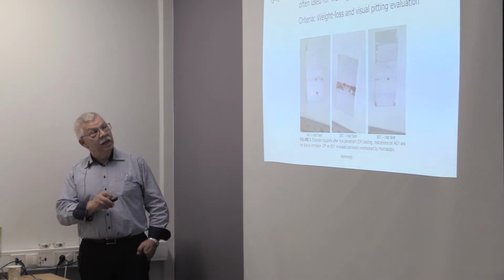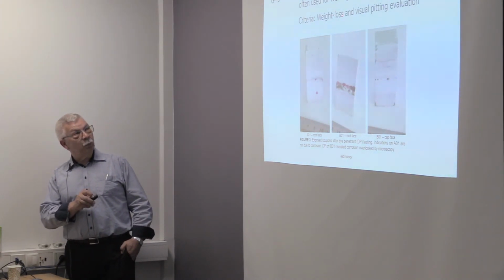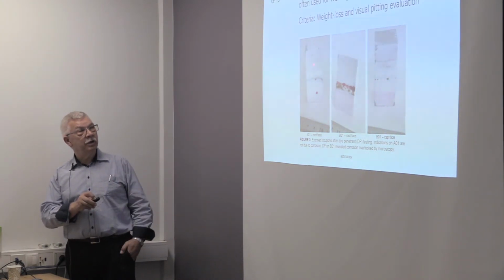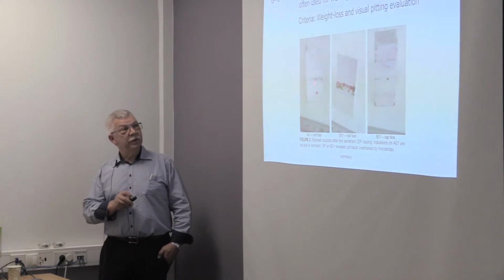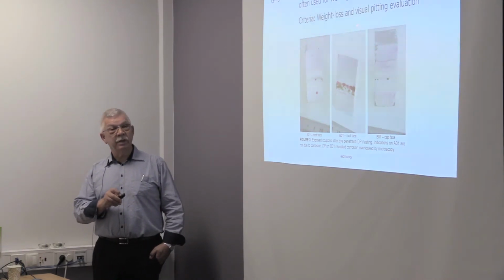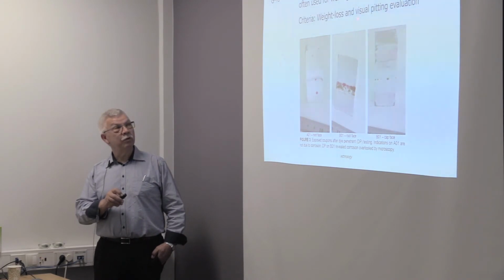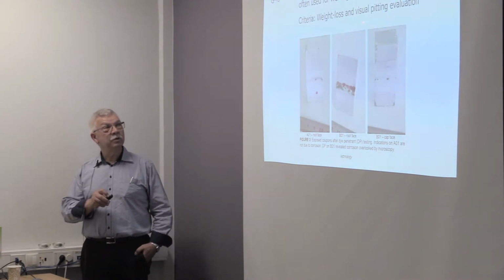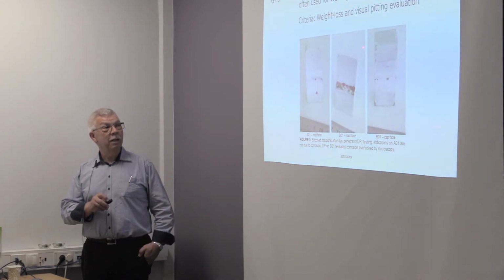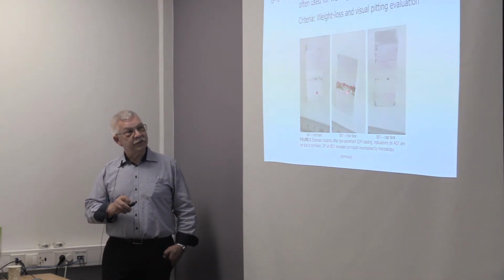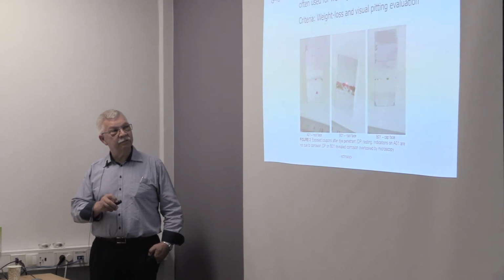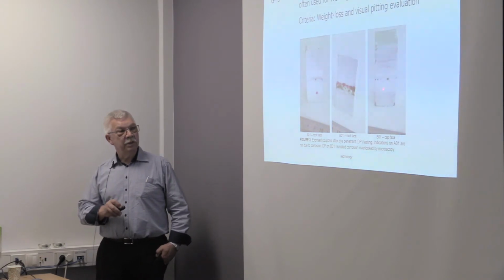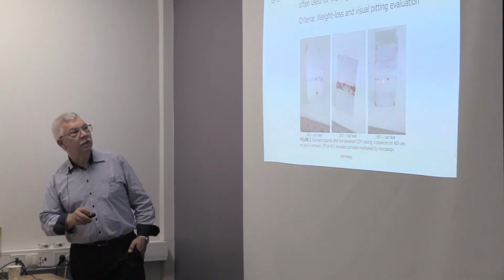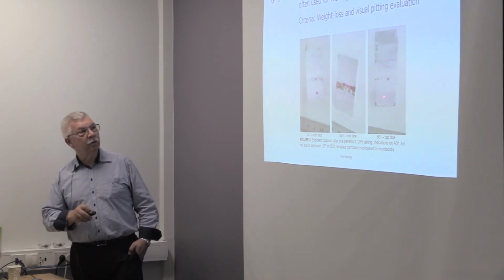There are some pits. The evaluation is that the weight loss in the test has to be within a certain limit, and there must be no visual pitting examined in a microscope at, I think it's 20 or 40 times magnification. You should not see any pitting corrosion. And here we have had some help from dye-penetrant testing to find the pitting. So this one is failed due to pitting from the test media. And this is the cap side, I think, and no problems with corrosion there.